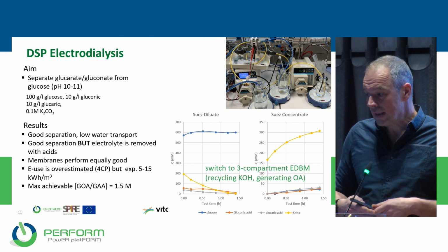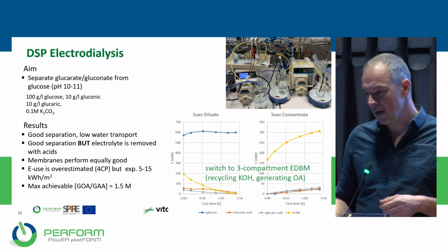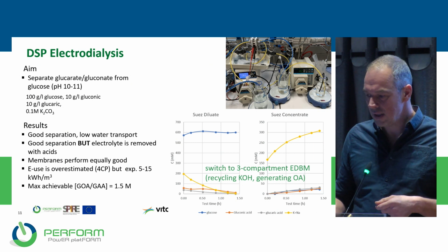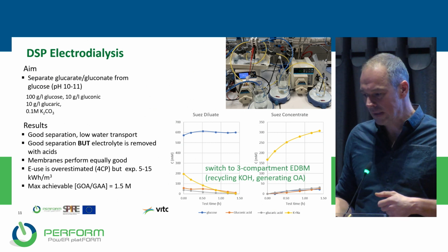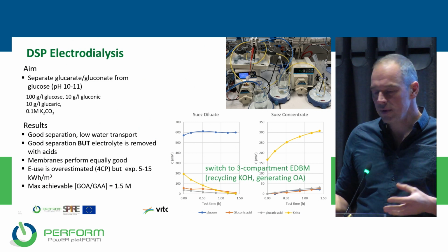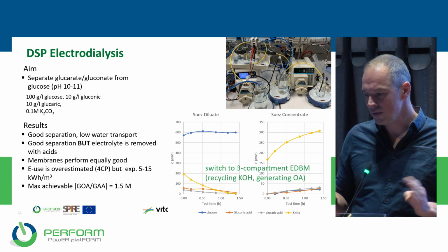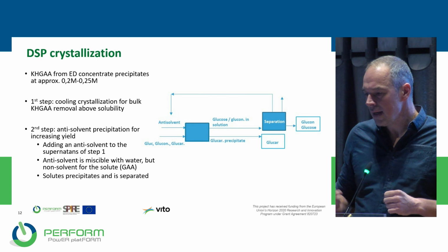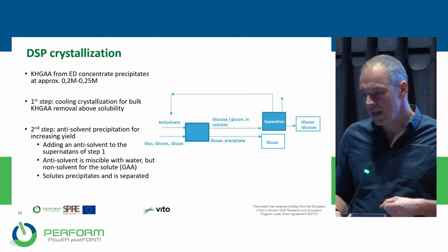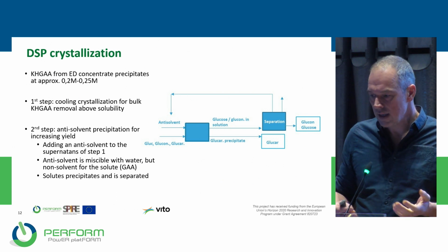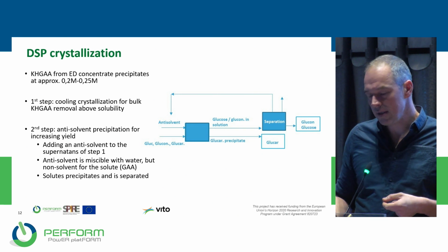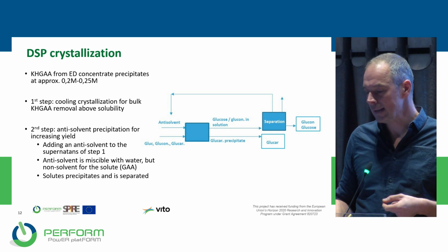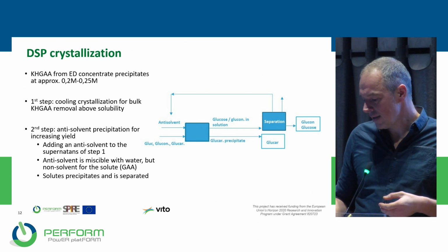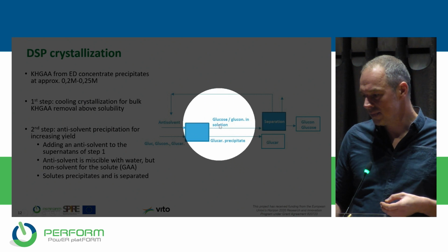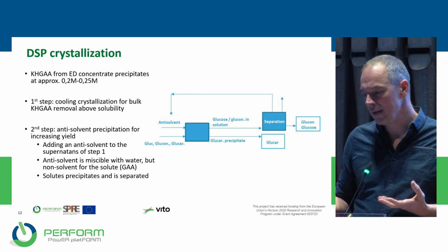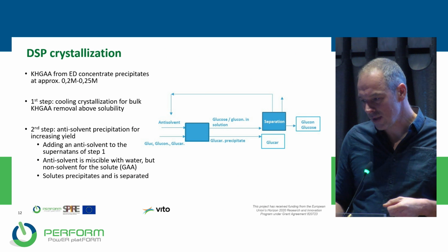Of course, as I mentioned, a DSP also needs to be in place in order to remove the mediator from our electrolytes. The first step that we investigated was electrodialysis, similar to line 1, where we could see that we could achieve a very good separation of glucose from the formed acids, both gluconic and glucaric acid. I will quickly go over this. Following then the final step of the downstream processing, the DSP, for the crystallization, we saw that we could actually selectively precipitate potassium monoglucarate from the reaction electrolyte, so separate it selectively from glucose and gluconate. So it's a way to selectively separate the gluconate from the glucarate.